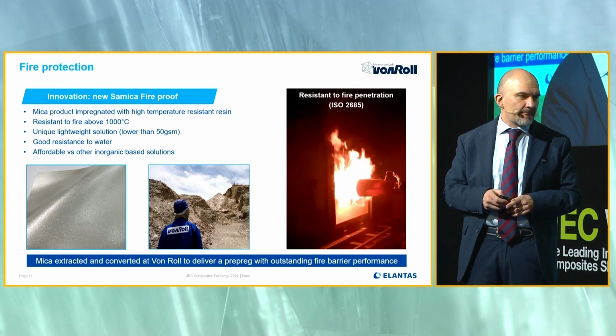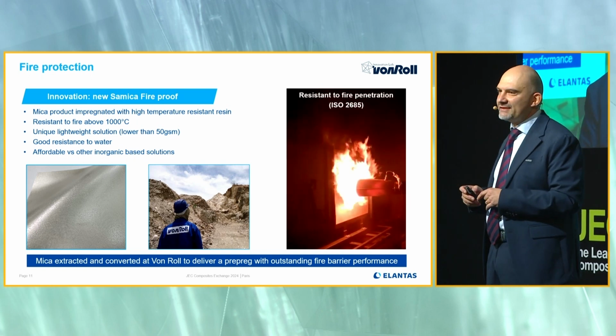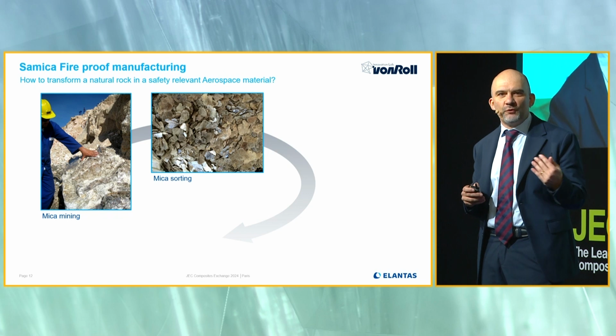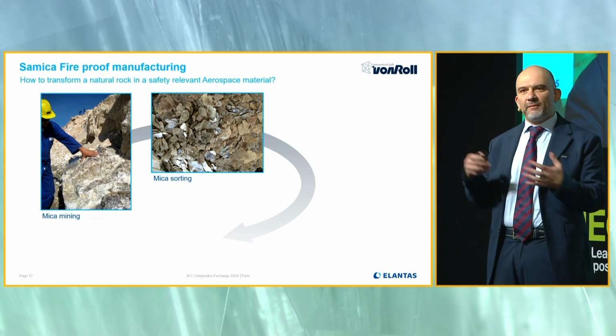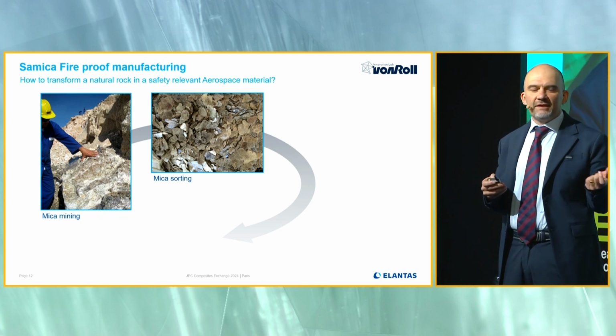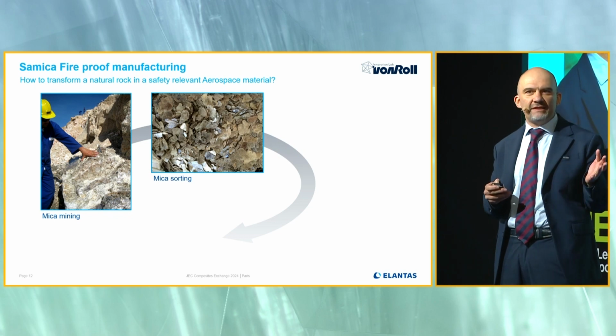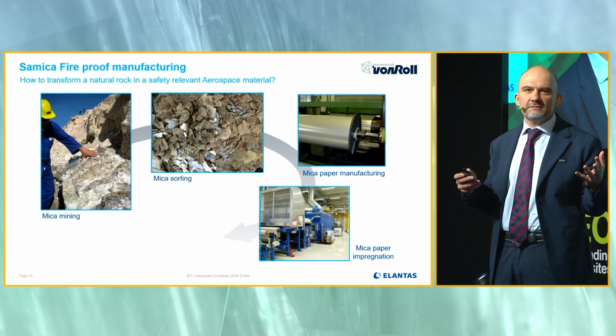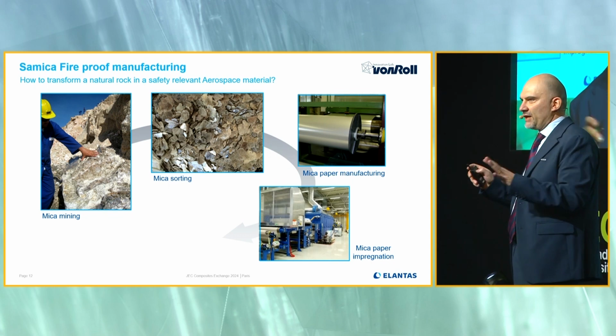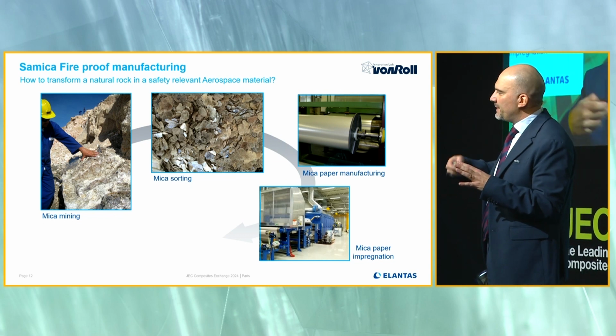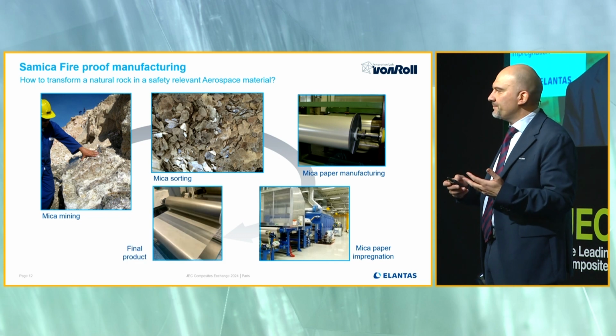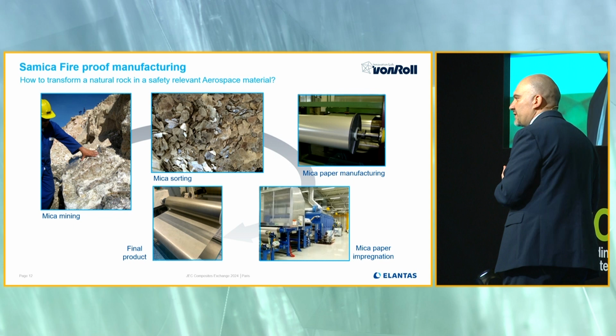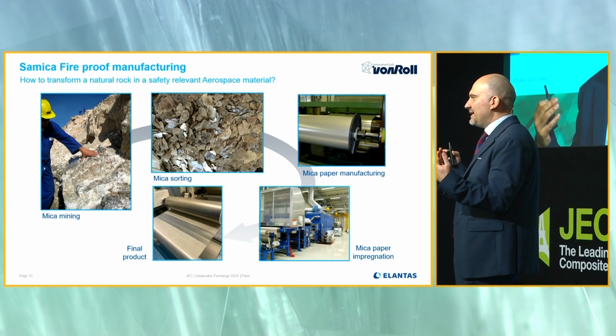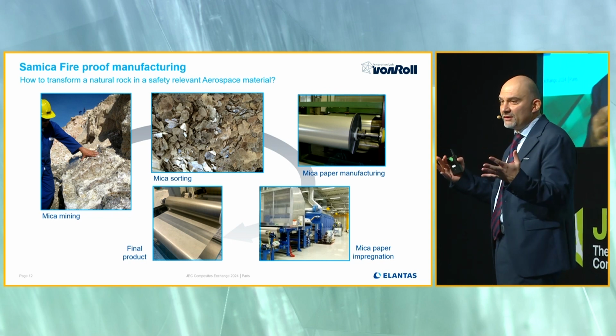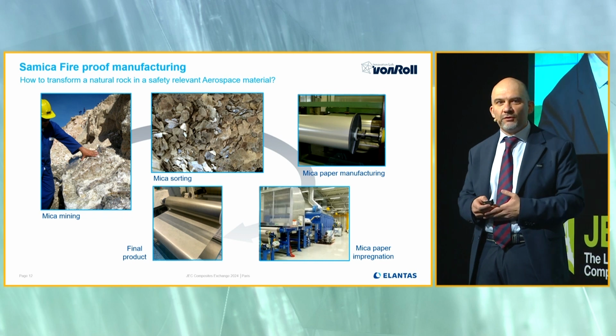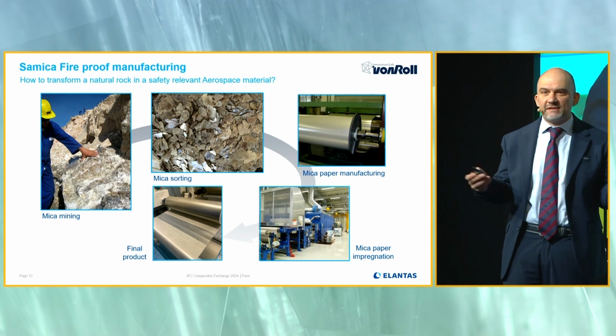part 7. You see some pictures of mines in this chart, and this is because in our company, we extract this mica material from mines, and we transform it into flakes, which are sorted, and then they are transformed into a paper. A paper which is fundamentally a 100% inorganic product, which is then laminated and impregnated with resins. And then this is transformed into a product which is suitable for this application. And it's really impressive, I think, to see how we can make use of a natural product, fundamentally a rock, in something which is so important for the community in general, for all the passengers traveling all around the